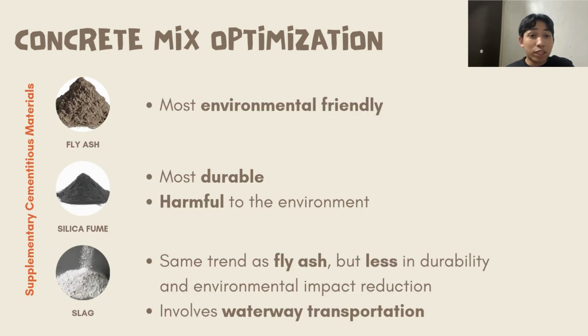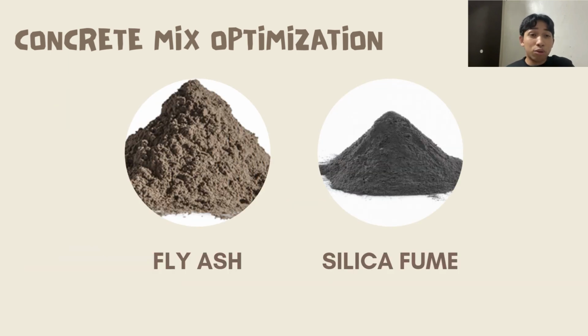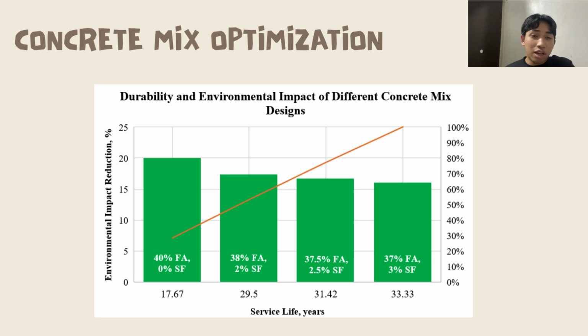As a recap, fly ash was the most eco-friendly, while silica fume was the most harmful but produced the most durable concrete. Slag had the same trend as fly ash, but less in both parameters. Also, slag involves waterway transportation, which is impractical since our location mainly uses roads. Given those, the team chose fly ash and silica fume. The team decided to work around fly ash since it was the most friendly, but also added minimal silica fume to capitalize on its high durability.